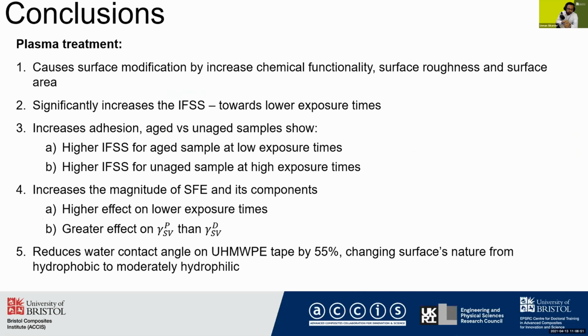So finally, plasma treatment does increase chemical functionality. It does increase the IFSS on the samples, which is higher at lower exposure times for aged samples, and higher for unaged samples at higher exposure times. The total surface energy and its components increase, which is affected more at the lower exposure times, and also the polar component is affected more than the dispersive component. The water contact angle reduces by 55%, which means that the surface goes from hydrophobic to moderately hydrophilic.